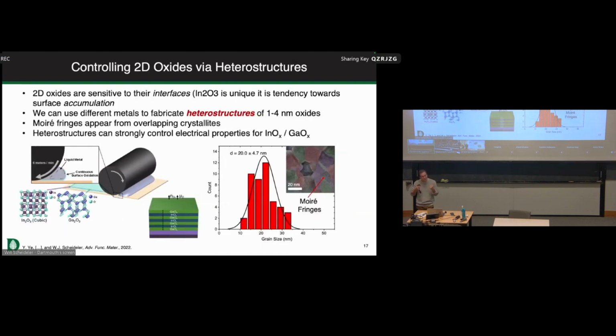Okay, so because this material is really thin, there are a lot of other interesting things we could do with it. So like other two-dimensional materials, indium oxide is sensitive to its interfaces to a really high degree. Now it's different from some others because it doesn't typically demonstrate surface depletion. It demonstrates surface accumulation instead. It wants to be really conductive even when you make it thin.